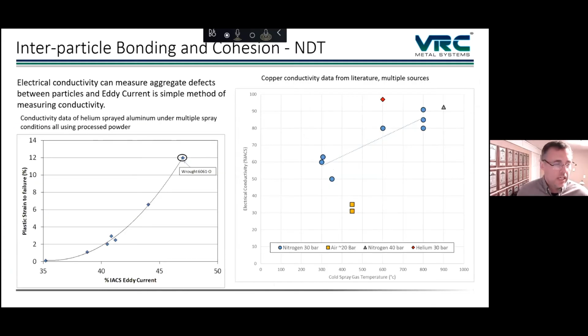You can also see this in things like conductivity. So this is an example of, on the left, plastic strain to failure for a 6061 cold sprayed material versus the conductivity from an eddy current test. So this is electrical conductivity. And you can see that as you increase the plastic strain to failure, the eddy current response is much higher, where raw material is way up there at the top. In some cold spray cases, we're more than half of what the raw material shows.